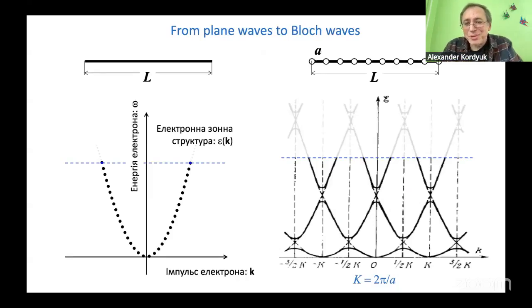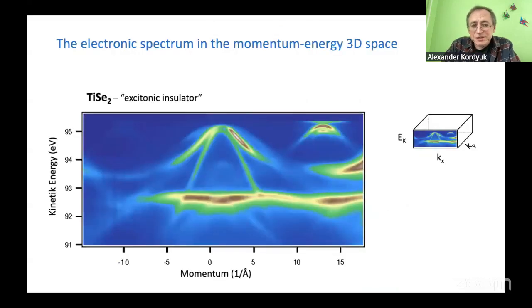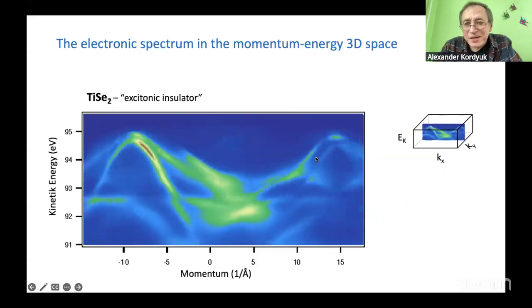This would, of course, take much more time, but briefly, if we have not just a uniform sample but a periodic crystal structure and periodic potential, then instead of the free electron parabola you have this parabola shifted. You have something like a Fourier transformation of this interaction. This is called Bloch electrons. It means that instead of one parabola you have a number of bands, and you have a new scale in the reciprocal space, called the Brillouin zone size, or reciprocal vector. This vector is inversely proportional to the distance between atoms in the atomic lattice.